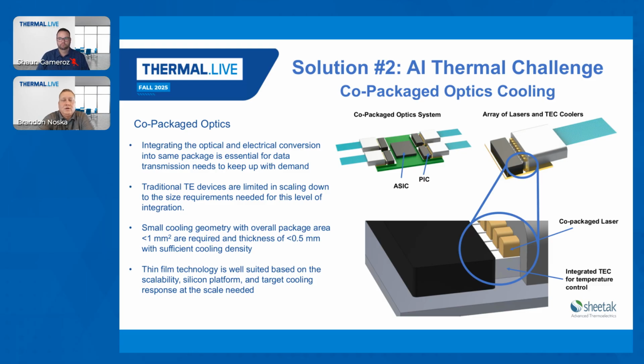for this type of implementation and co-packaging. With the bulk devices, it's very hard to scale down much below the sizes that I was just talking about, something that's maybe 2 millimeters by 2 millimeters, or 5 by 5, or even down to 1 by 1 millimeters. Some of these laser diodes and such are half a millimeter by half a millimeter, or 0.6 or so. And in order to scale down to that size, you really need some new technology or some change in the technology in order to address that. And that's where the thin film technology can come into play.